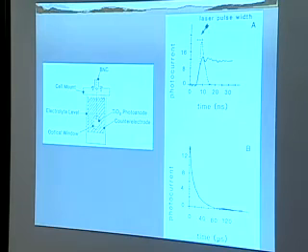So we have a TiO2 electrode now. For those of you who don't do photoelectrochemistry, it's light sensitive is all you need to know. And the only time an oxidative current is going to flow is when the light's turned on. It turns out it's a non-trivial experiment in that you have two things to be concerned with. What you're going to do is take a little TiO2 single crystal electrode that's right here, and hit it with a pulse of light from a laser. This was in the 80s, so a fast pulse was several nanoseconds, not femtoseconds, but a moderately fast pulse.